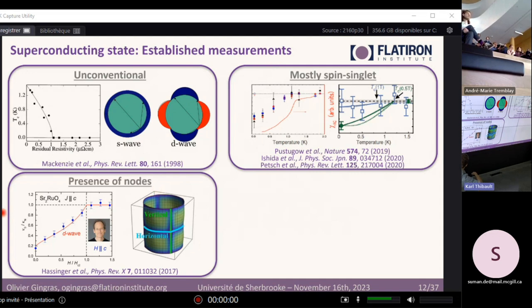Another important aspect here is the presence of nodes on the Fermi surface. That has been shown by thermal measurements, by transport measurements, particularly in the group of Louis here. And what it shows is that even at zero temperature, there is still a residual scattering of the Cooper pairs. So this is an indication that you have a very small gap, or in particular a node, because it remains at zero temperature. There's always the issue of the size of the temperature, which can be a problem, but they went low enough to be able to state that there were nodes on the Fermi surface. And in particular, the behavior of these nodes is extremely similar to what you would expect from a textbook D wave.